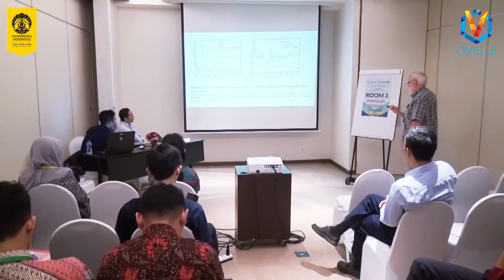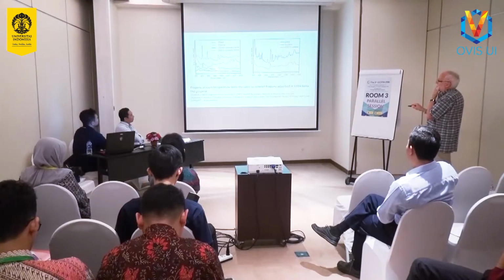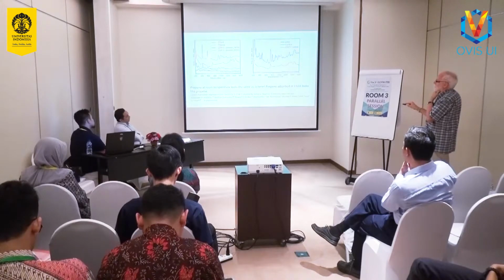If we, however, do an experiment of absorbing the propene at lower temperature, then we see something different. So the blue trace here is propene which has been absorbed not at room temperature, but at 140 Kelvin. When we look at that spectrum, you see that we've got back the vibrations which are due to the olefin: carbon-carbon double bond, and out-of-plane bending modes of the olefinic hydrogens. In particular, these two have come back. If we put propene in at room temperature, they're not there.